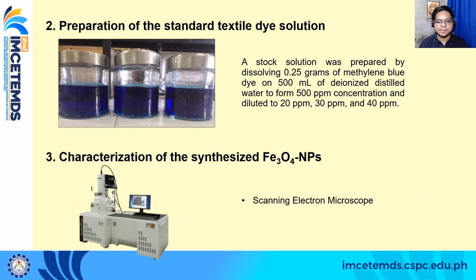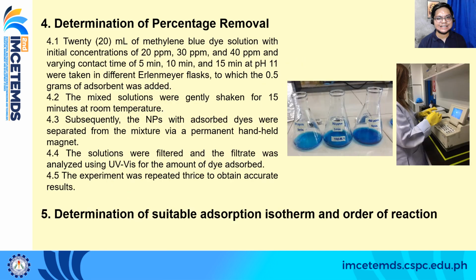Next is the preparation of the standard textile dye solution, and then the characterization of the synthesized iron oxide nanoparticles, where we used SEM, or scanning electron microscope, in order to determine the shape, the particle size, and the pore size of the synthesized iron oxide nanoparticles. Next is the optimization of the varying parameters.